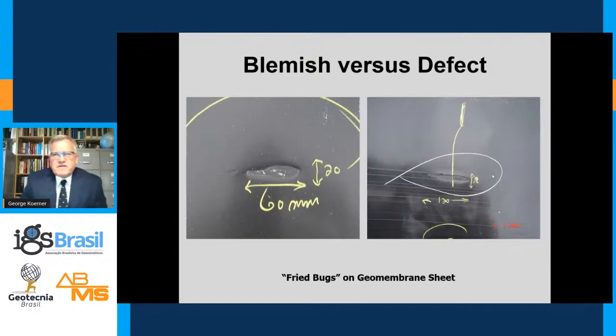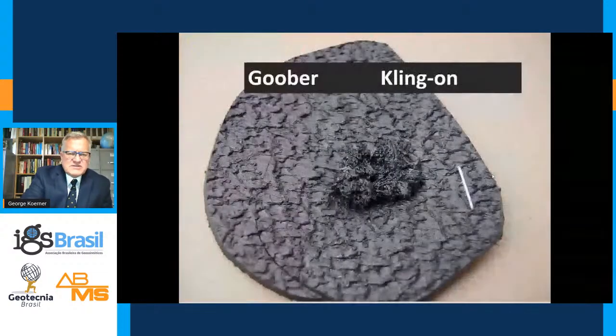Okay, I showed you a perfect world in those photographs. There are problems which are associated with the manufacturing of geomembrane, and certainly the QA personnel have to pick up on this. Things that are out there, I won't show you all of them, but when an imperfection like this occurs, you have to establish, is this a defect or is it a blemish? The difference in definition of this is a defect is something that does not conform to the specification. Values fall below the specification values. Obviously, in this case, if you would run a tensile test or a thickness test, this is much more than a blemish. It would certainly be a defect.